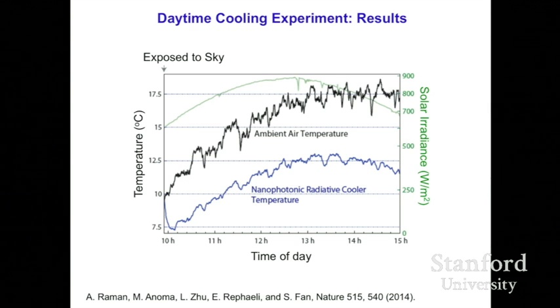One of the very interesting things actually occurred in the very beginning of the experiment. When we start the experiment, the cooler is covered, and therefore it doesn't see the sky and has a temperature that's comparable to the ambient air temperature. Now, when we take out the cover, for most of us, the everyday experience has been that if you go out of the shade into the sun, well, you see the sun and you will be hotter. The radiative cooler actually does exactly the opposite. When it sees the sun and therefore sees the sky, its temperature drops very quickly. And that, of course, is a key experimental signature of radiative cooling. Radiative cooling requires you to have radiative access to outer space. And in this regard, you can see that exposure to the sky leads to the temperature drop.